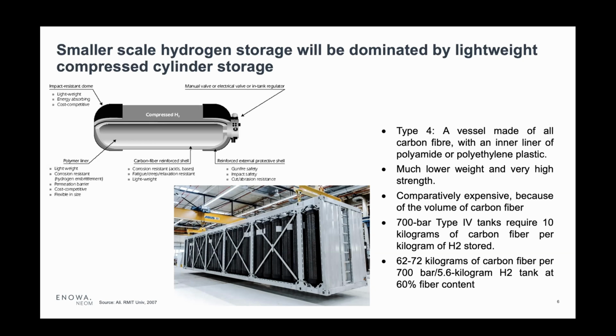These vessels are type 4. They can go up to 700 bar, and they're much lower in weight than your typical steel vessel of comparable rating. A typical 700 bar tank, type 4, would require 10 kilograms of carbon fiber per kilogram of hydrogen. A vehicle might carry about 5 to 6 kilograms of hydrogen. So then you need about 60 to 70 kilograms of carbon fiber to be used inside of that storage vessel.